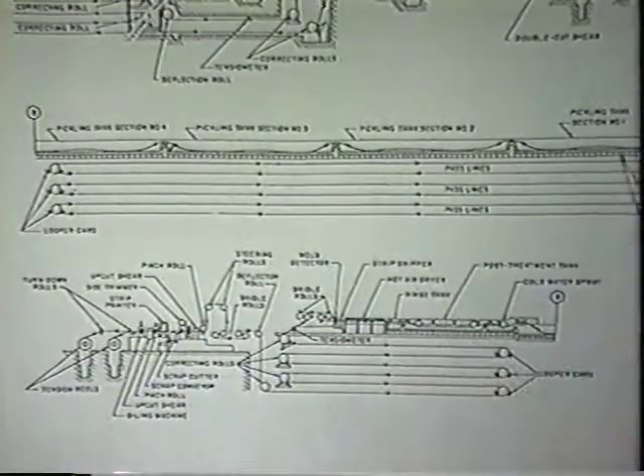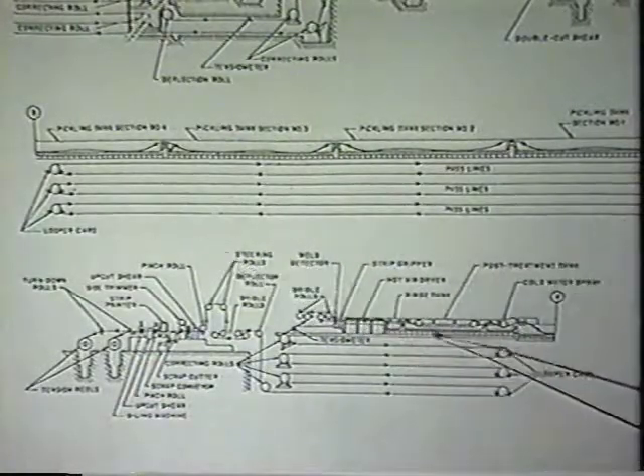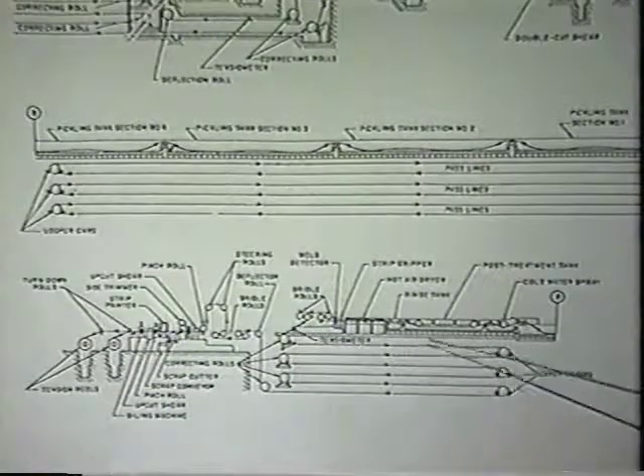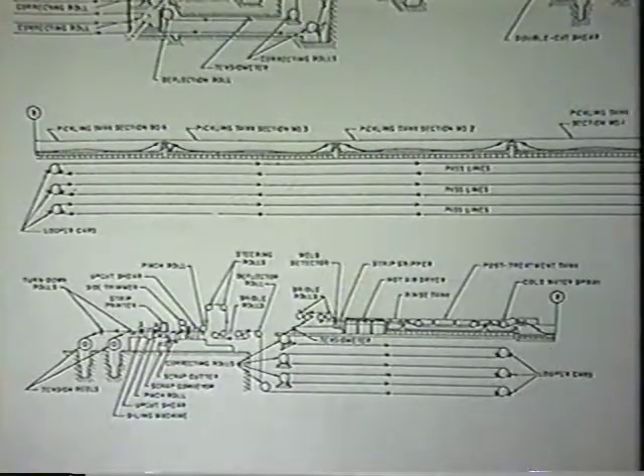Once we go through the pickle tanks, and this is where we are removing the scale, we go to an elaborate rinse area. Several rinse tanks, sprays, wipe-offs. It's very important that when the pickling operation is complete, all of the acid gets removed. If we don't remove the acid, the strip will rust later on. It'll rust later on because we're using hydrochloric acid, lots of chlorides. Chlorides have an affinity for moisture. Any chloride that is left on the strip will soak up any available moisture in the atmosphere. It'll also pull moisture through slushing oil. It's important that it be removed. If it's not removed through this rinse, it'll rust.